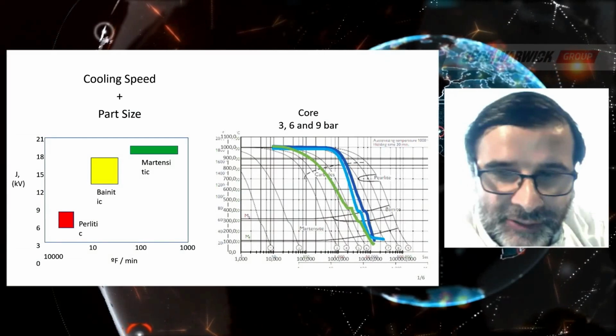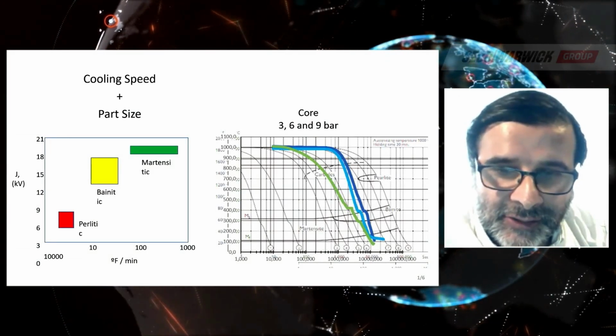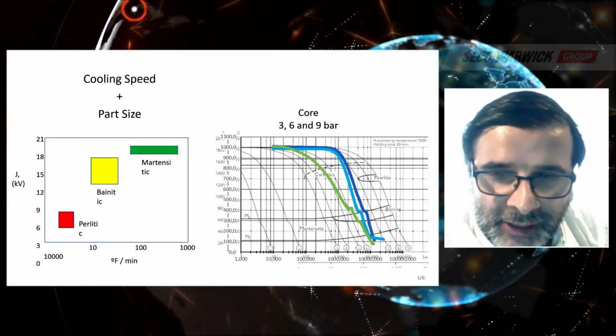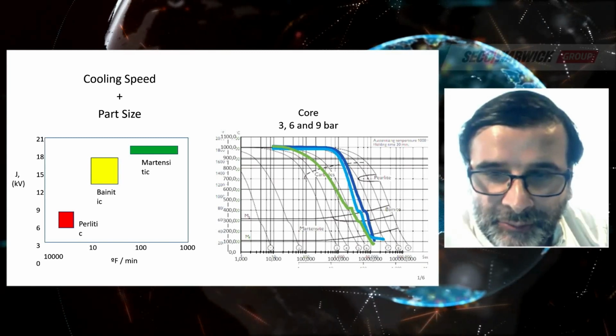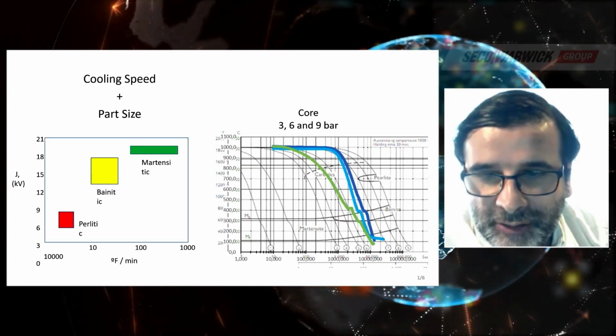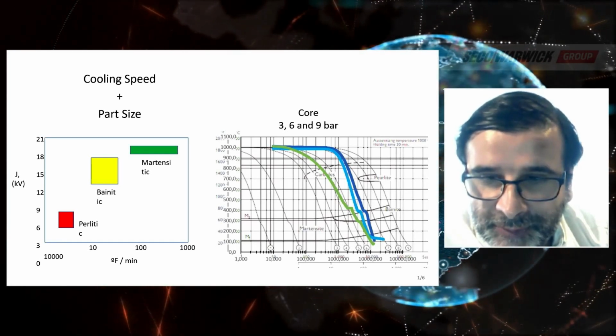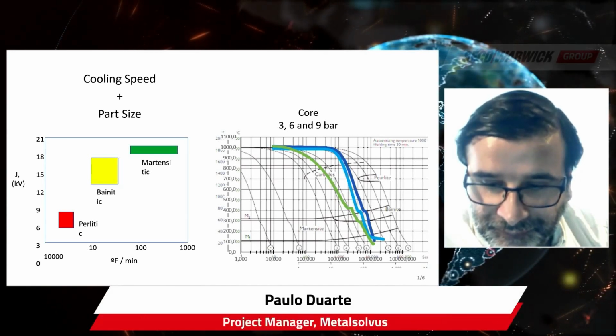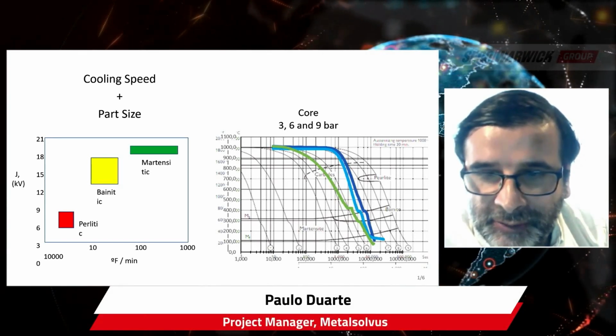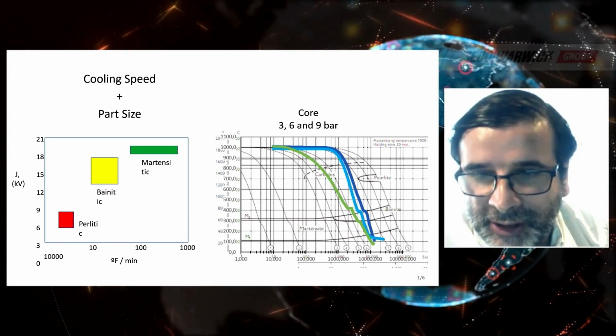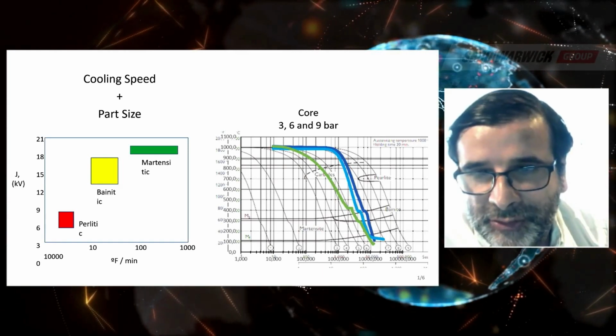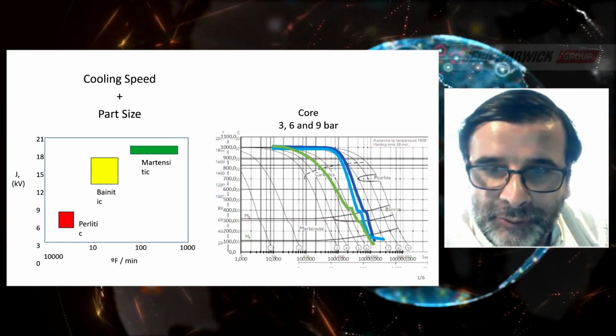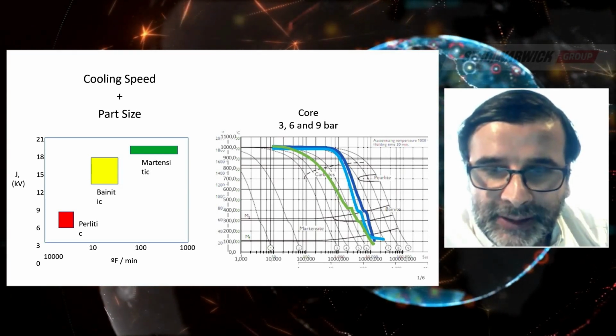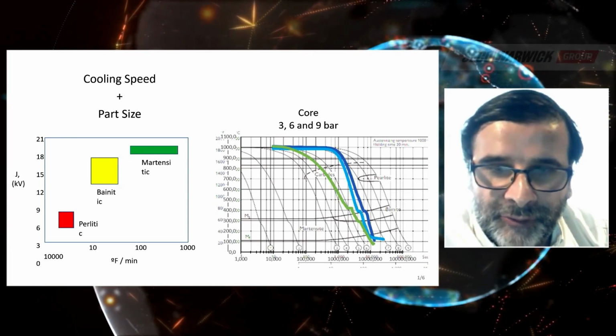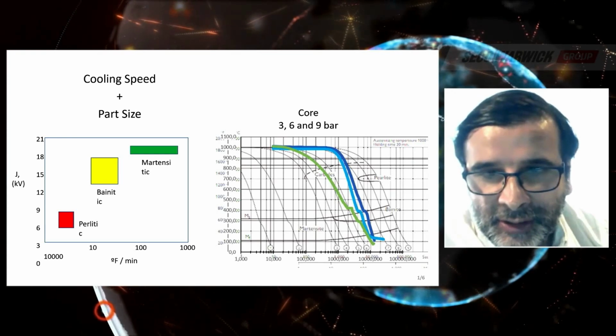I can start. So what happens is that when we increase the size of the die, if the thickness gets big, maybe even if we put more pressure on the furnace, the part will cool at lower speed. We can cool it faster, but the part is thick, so we cannot extract the heat so well. So this means that when we increase the size of the die, the cooling speed of the part is just like we see in this T diagram.